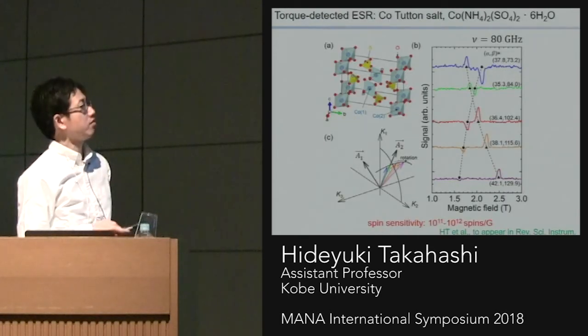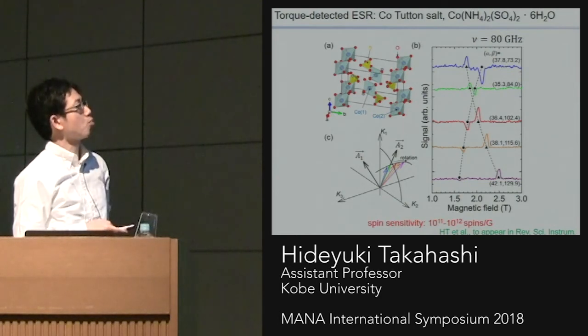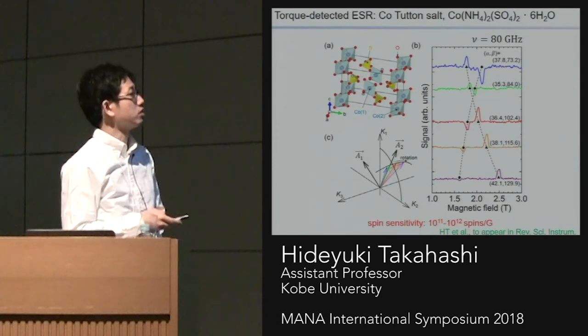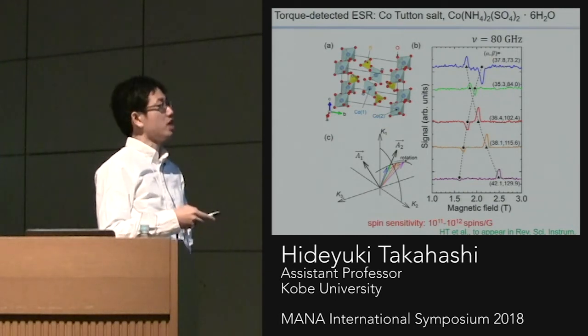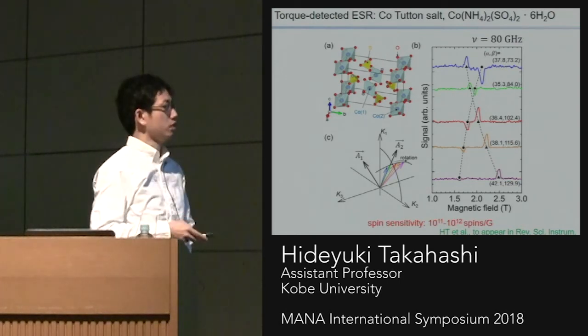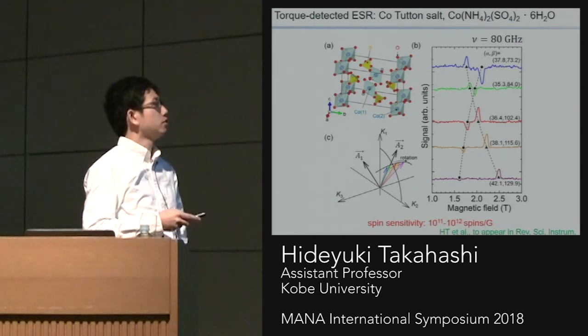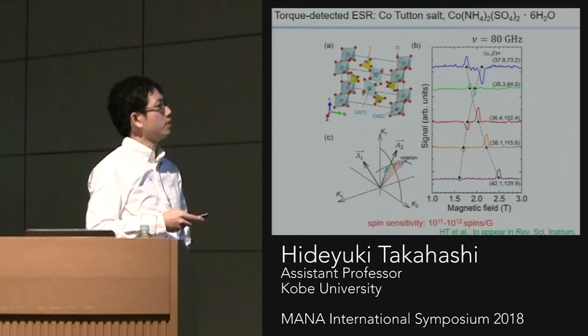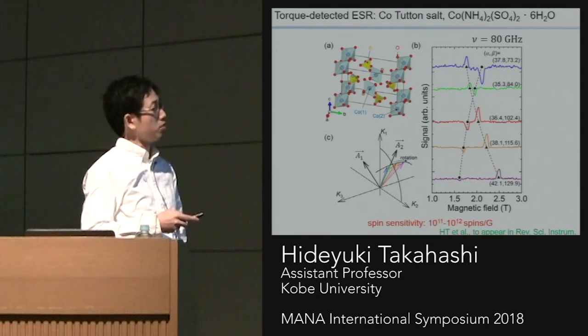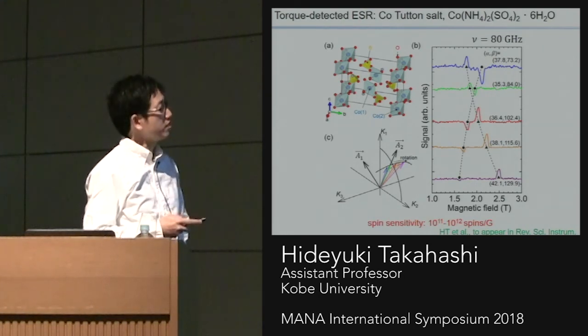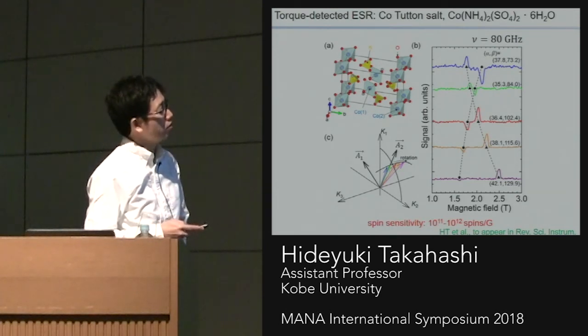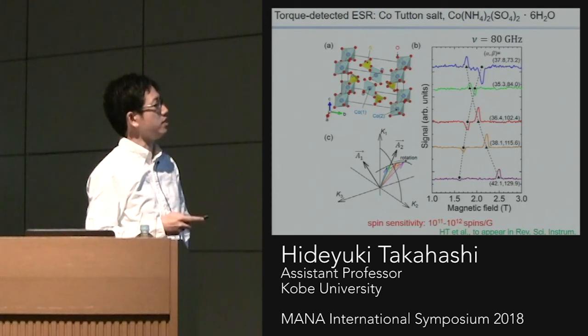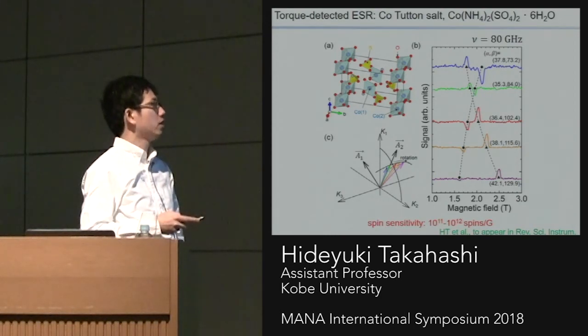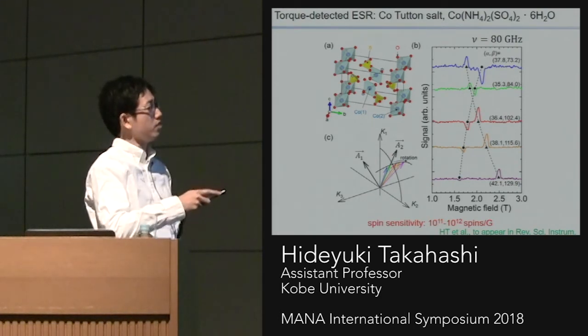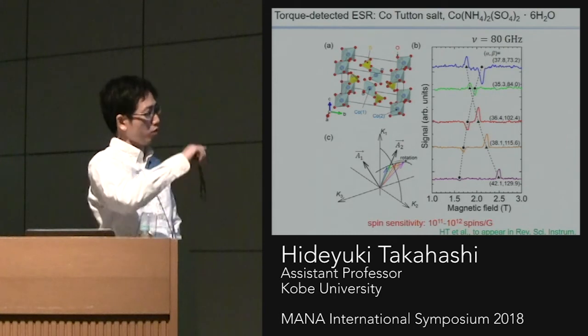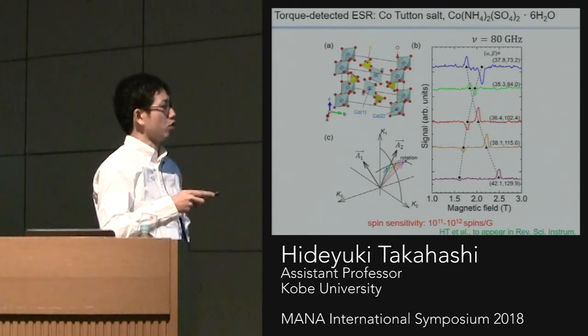And we also applied this technique to the ESR measurement of cobalt Tutton salt. We used this compound because it has relatively high spin density, and it also has magnetic anisotropy. The magnetic ion of this substance is cobalt 2+, located at the center of this octahedra. And as you can see, there are two inequivalent sites, cobalt 1 and cobalt 2. These are the origin of two peaks in the ESR spectrum. And as the angle between the symmetry axis and the magnetic field direction rotates, we observe the g shift along this line.